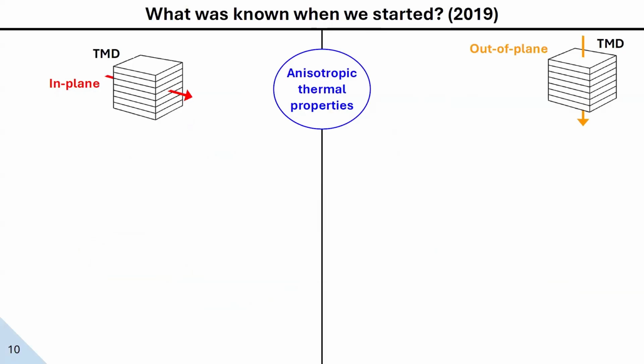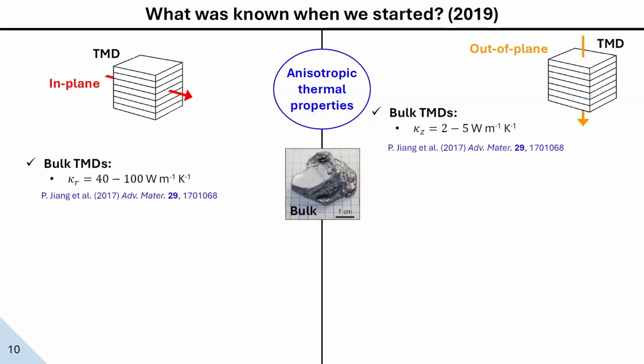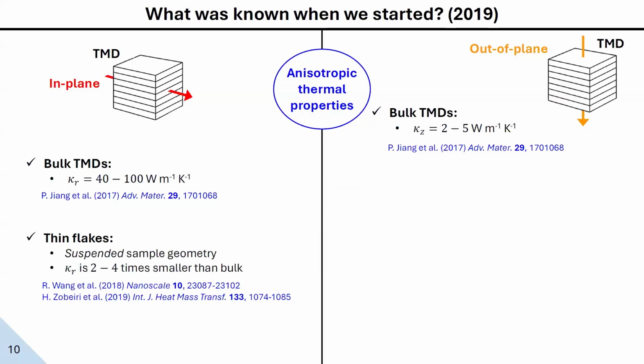So what was known when we started our research? First of all, we knew these materials are strongly anisotropic, so they propagate heat very differently in the plane or across the plane. The in-plane thermal conductivity of both TMDs is 10 to 20 times larger than the out-of-plane thermal conductivity in these materials. And what happens when we decrease the thickness? Well, for thinner flakes, typically we study them in suspended sample configuration, and this is because we don't want to have interactions with the substrate. We want to make a thermal gradient where the heat only flows within the plane in our crystal.